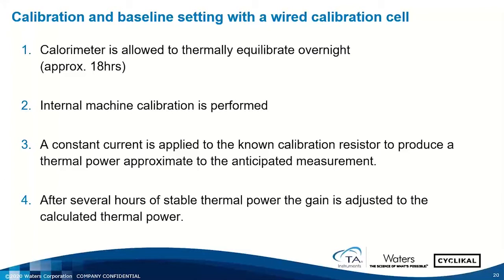So that constant current then is applied for a few hours until we get a stable thermal power from the calorimeter. And after that thermal power is stabilized, we'll then adjust the gain through the device tab to equal the calculated thermal power. And the calculated thermal power, of course, is the current times the voltage. That typically tweaks the internal gain calibration constant a little bit. So the internal gain calibration is pretty much the bulk of the calibrations, but it's very important to do that tweaking of the thermal power to arrive at a very accurate gain calibration constant.